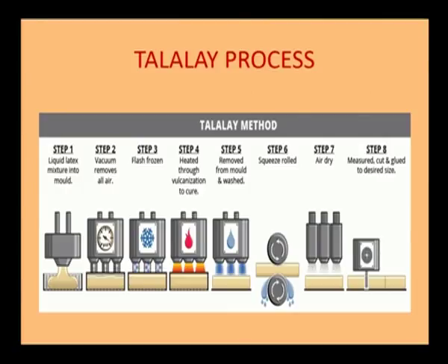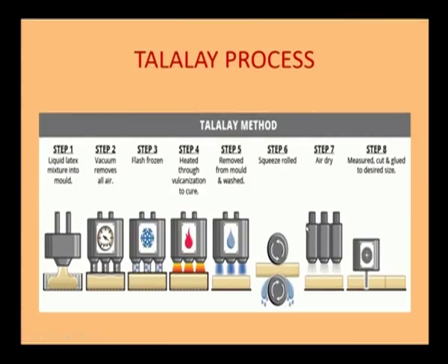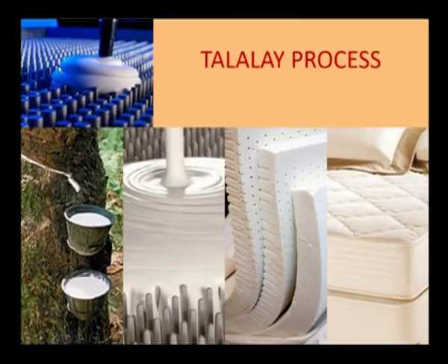While squeezing you are going to take out all the additives or ingredients which you have added and also the water particles come out. Then you are going to air dry it perfectly, then you measure it to a particular size, cut it, then you pack it. Here I have shown the images of the same process.